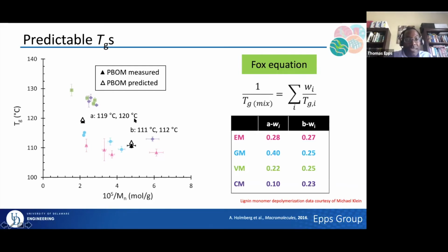And so what you can see here is that the data differ by about 1 degree, give or take, between the predictions and the measured data. This is one of the better samples. I will say that some of our worst data is off by about 5 to 6 degrees. So we're still very good and in the ballpark of having some good predictability. And I'll show you how we can use that a little bit later on.